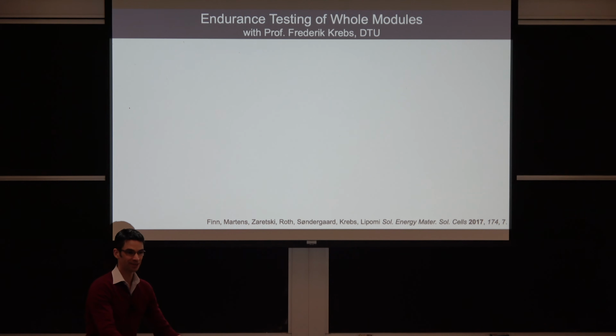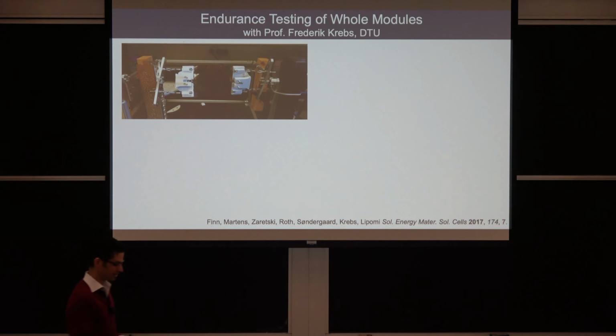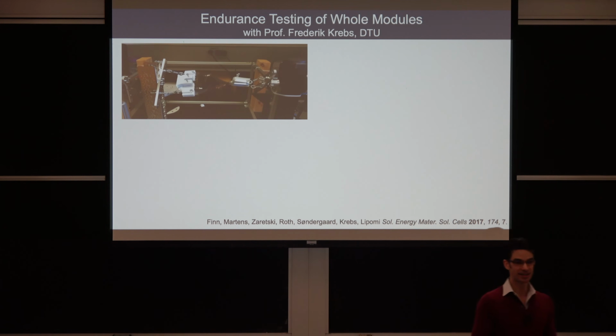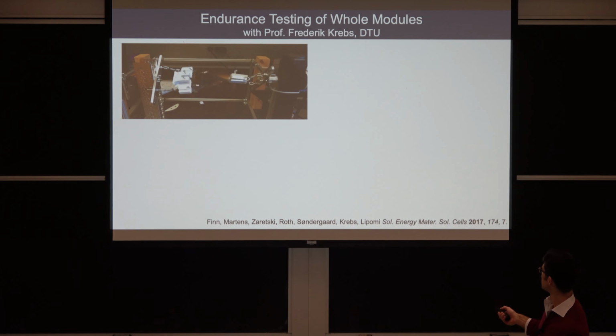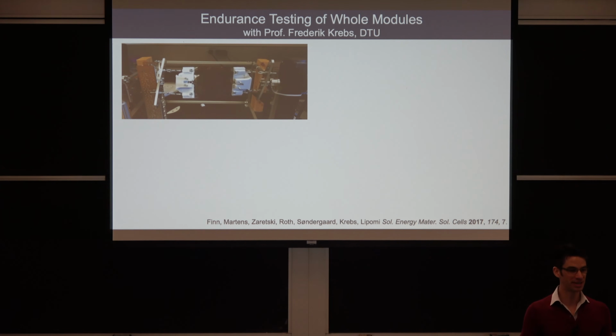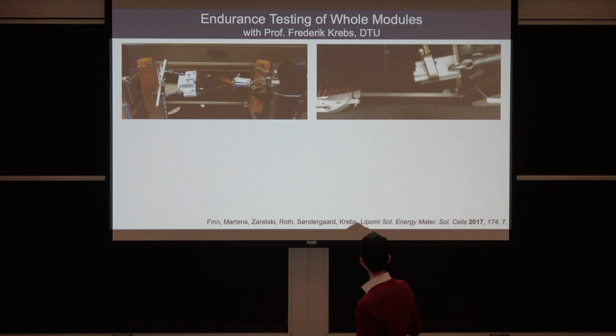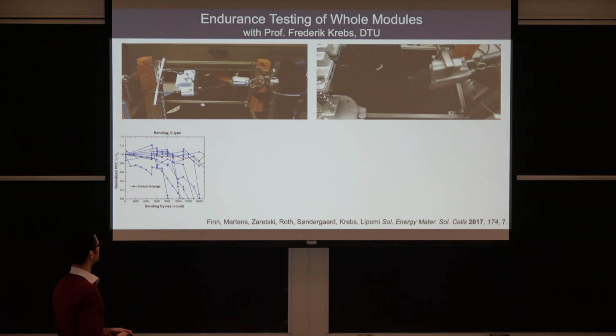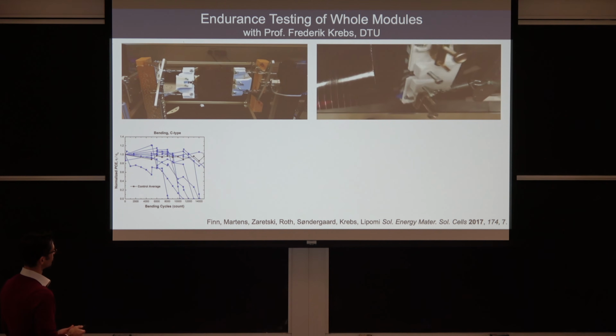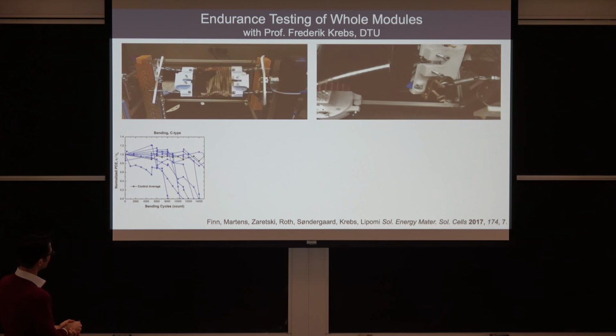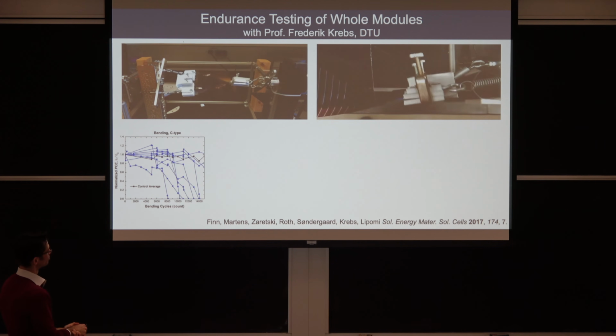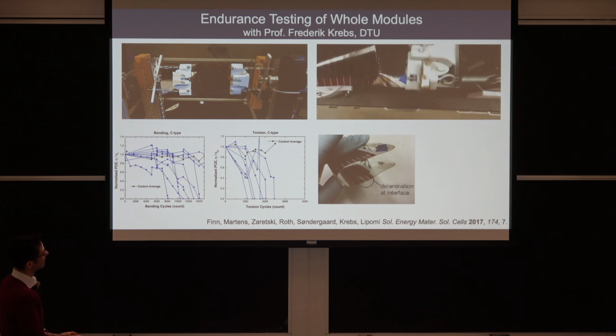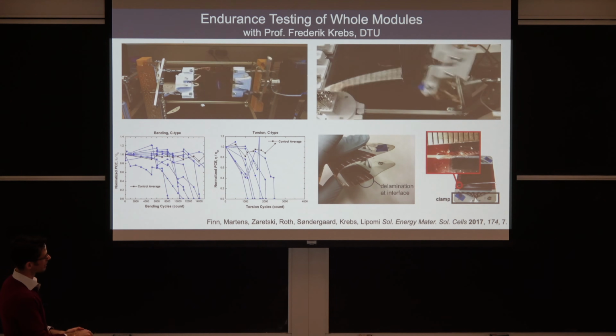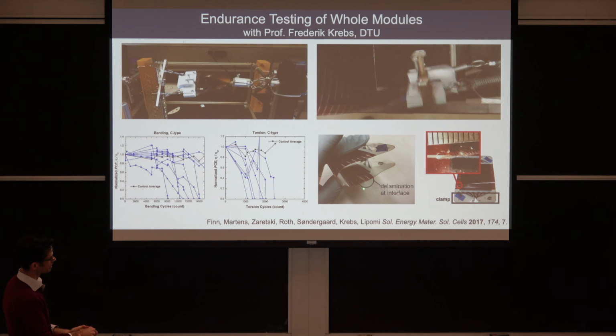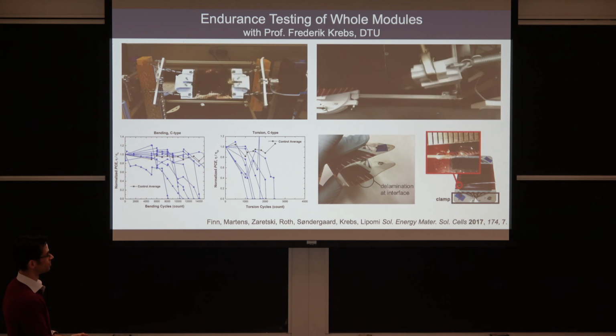So from the very tiny scale, we also looked at whole modules, and these modules were again made by Frederik Krebs' group in Denmark. And what we did is construct these solar cell torturing devices. So this is a twister. You can also reconfigure it into a bender, and you can get it to fail. And the goal is, after literally, I think we cycled like 30 cells, some total of like 1.5 million times. Some of these cells actually last more than 10,000 cycles of bending or torsion. And the goal of this research is to calculate and predict where in the device stack the materials are going to break down.